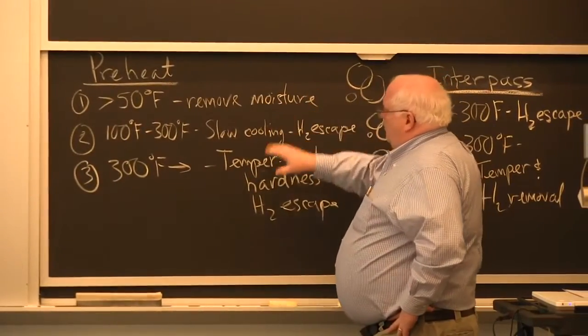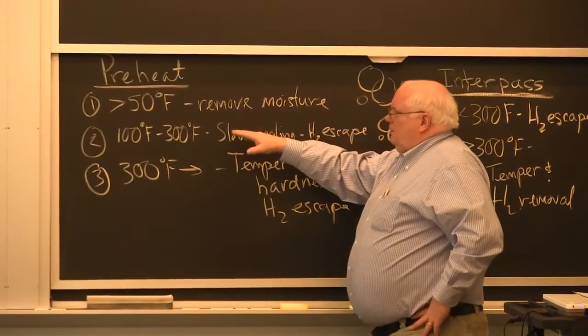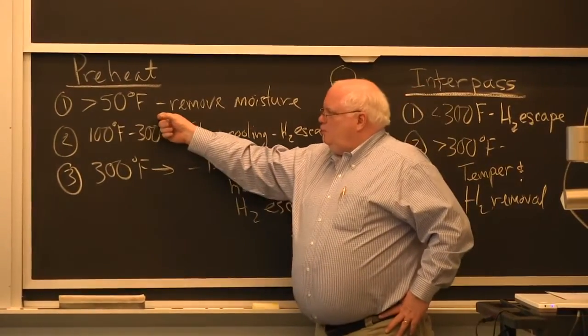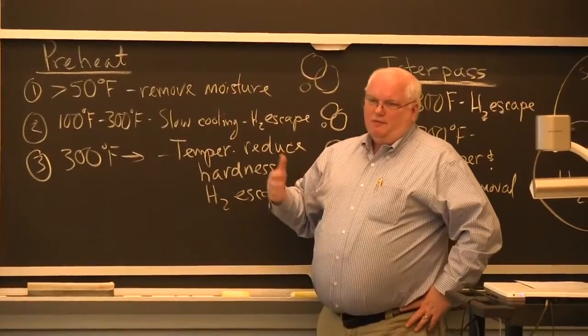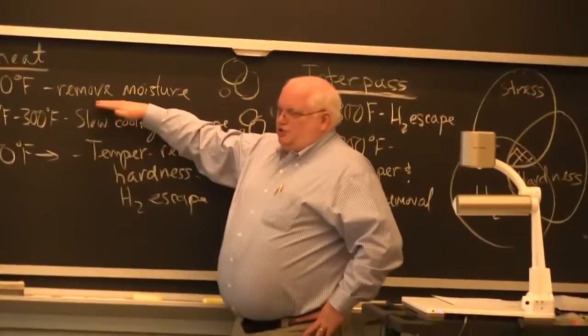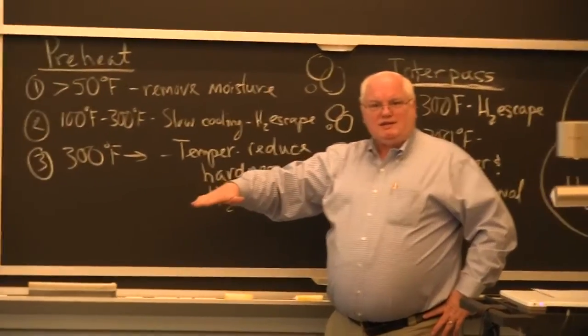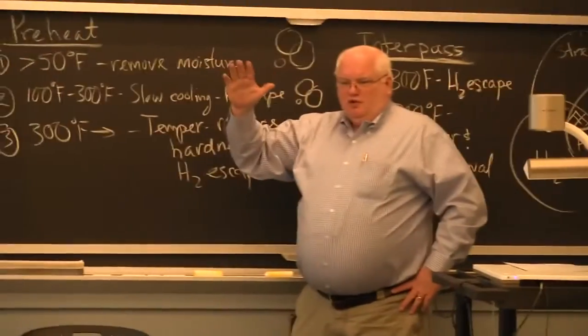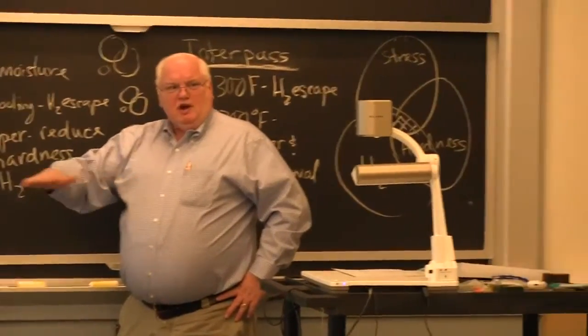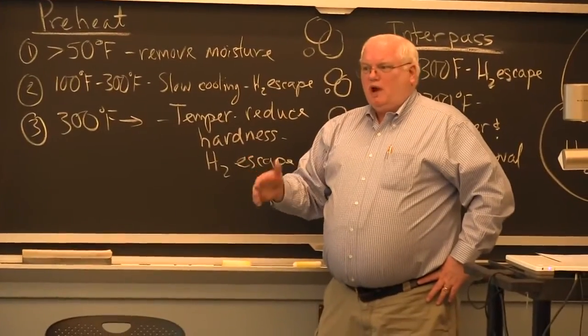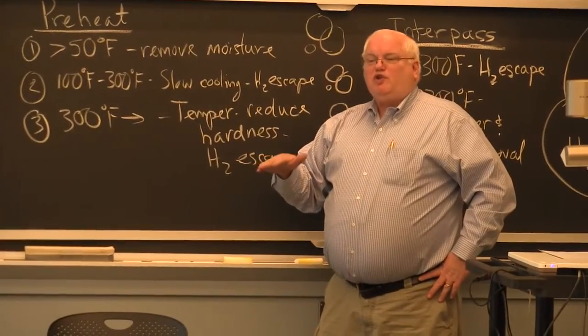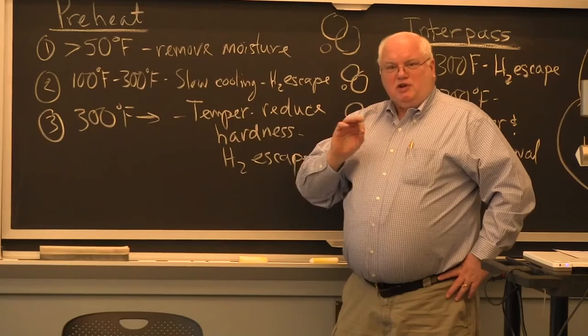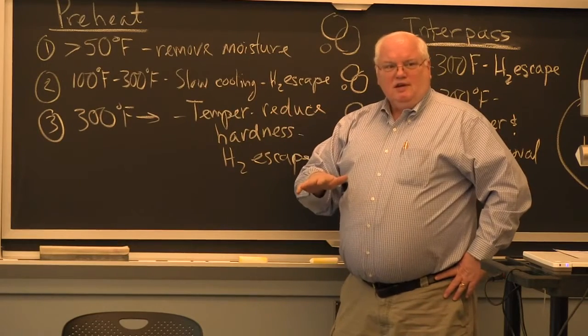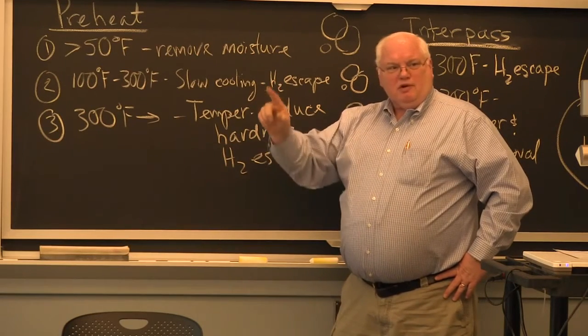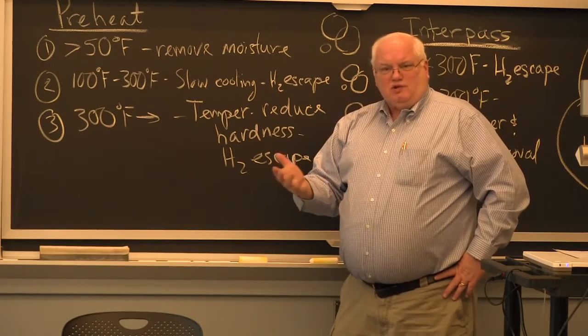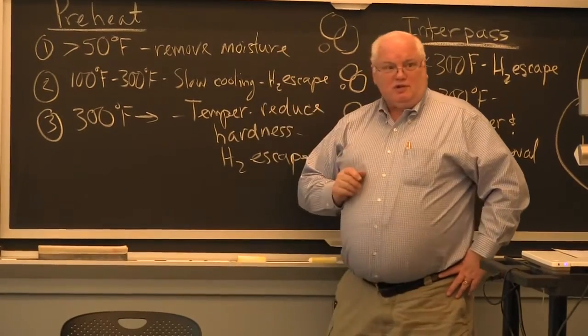Okay, so this is just a review of where we were. We talked about preheat yesterday, and you want to be at least above 50 degrees Fahrenheit before you start to weld on steel, just to remove the layer of moisture that you can't see. But as you know, if you get down to frost temperatures, you'll see the ice form on something and it turns white. But even before, at 33 degrees, there's actually a layer of moisture that condensed that you might even be able to feel at 33 with your finger, but you can't see it because it's water, it's transparent. But once it freezes, you can see the frost.